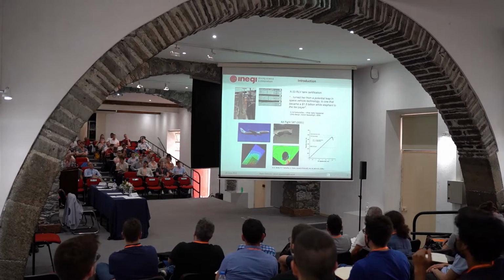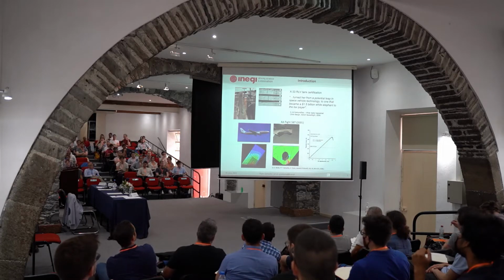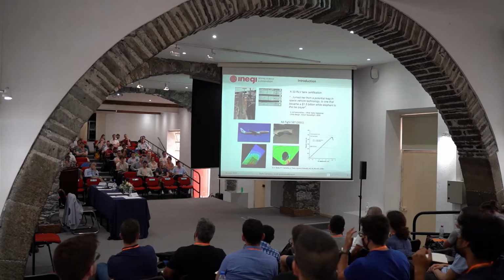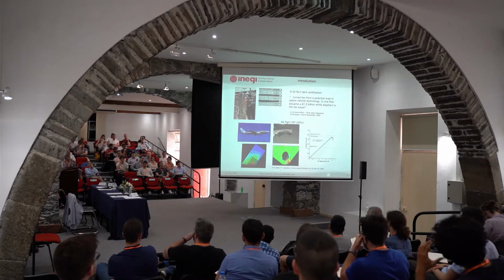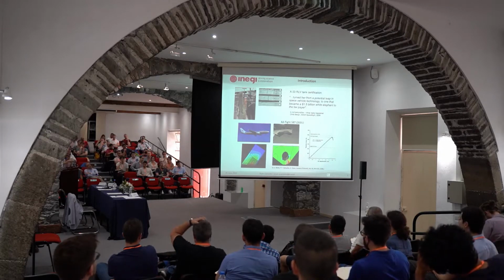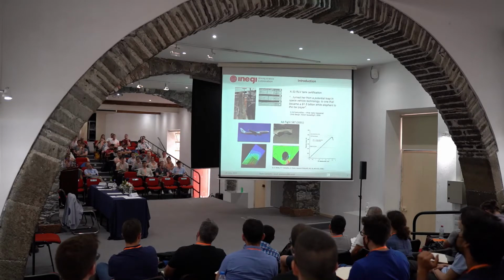We were able to show that the Airbus design was perfectly fine, so that was not the root cause of the accident. So this was very important to give confidence to the pilots and to the clients of this particular aircraft. Before Airbus actually performed physical tests, the lead time was 1 year, so this was done before. So I was not authorized to talk about this for 7 years, but in 2008 we published a paper in the Journal of Aircraft that, if you're interested, you can find more details in.